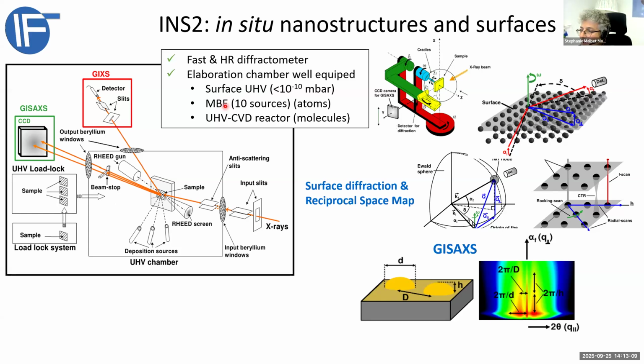Then you can make the growth of any heterostructure, thin film, or 2D material, just one layer of atoms or two layers of atoms, for instance. At the same time, you can also use this UHV chemical vapor deposition route, a chemical way. You can insert some gases into the chamber and make the reaction between molecules and the surface, and then combine physical and chemical routes to make the growth of anything. And you can now monitor during the growth.